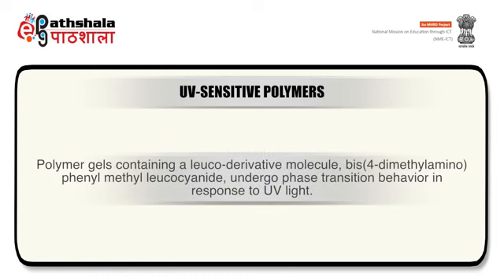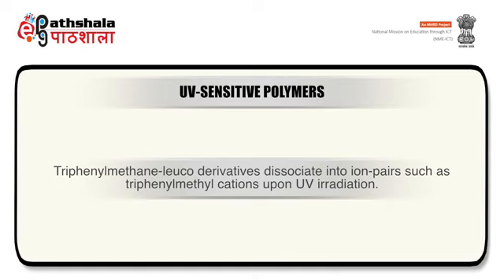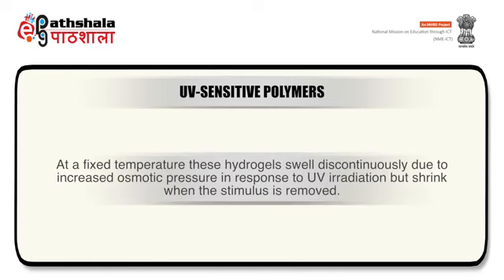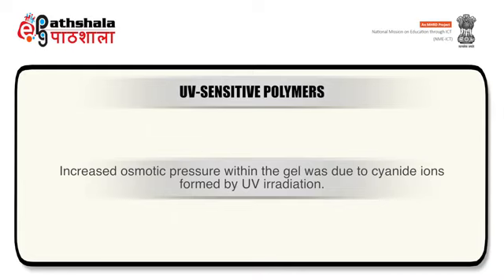Polymer gels containing a leukoderivative molecule, bis 4-dimethylamino phenylmethyl leucocyanide, undergo phase transition behavior in response to UV light. Triphenylmethane leukoderivative dissociates into ion pairs such as triphenylmethyl cation upon UV irradiation. At a fixed temperature, these hydrogels swell discontinuously due to increased osmotic pressure in response to UV irradiation but shrink when the stimulus is removed. Increased osmotic pressure within the gel was due to cyanide ions formed by UV irradiation.